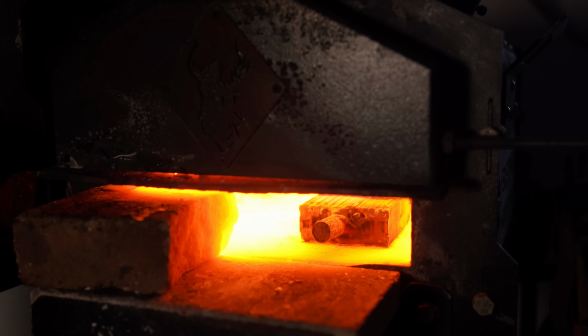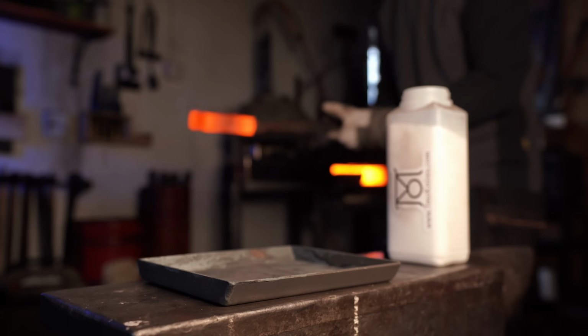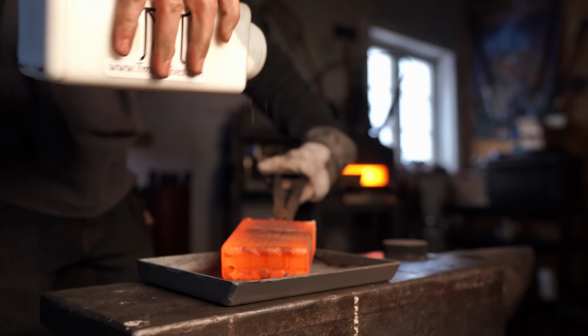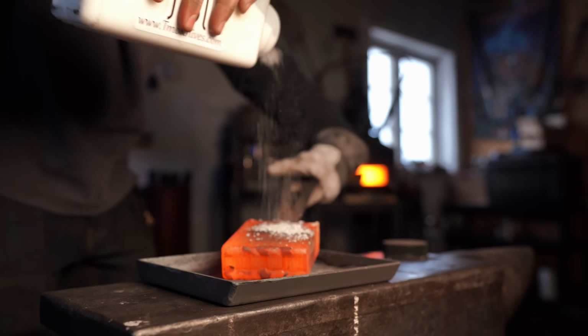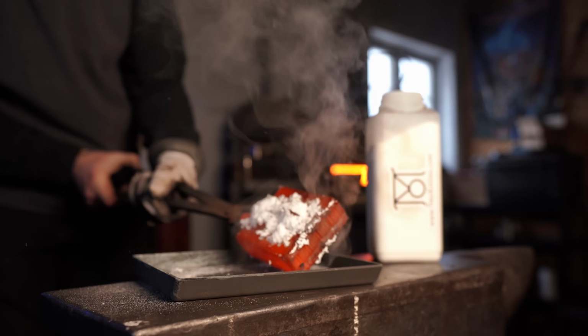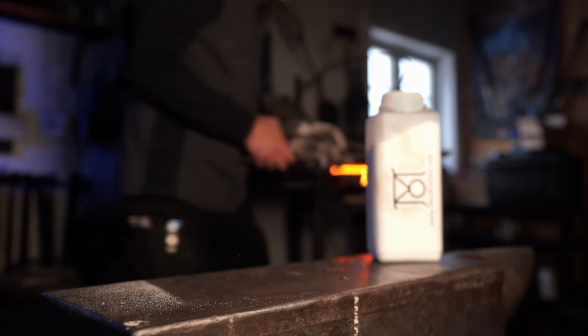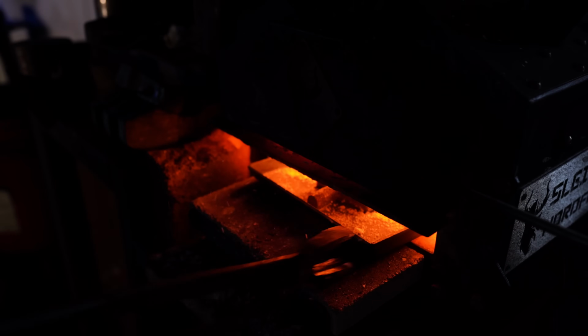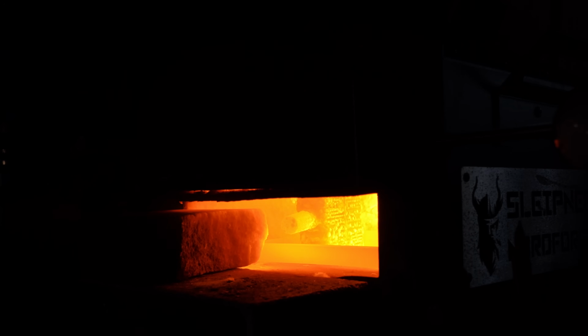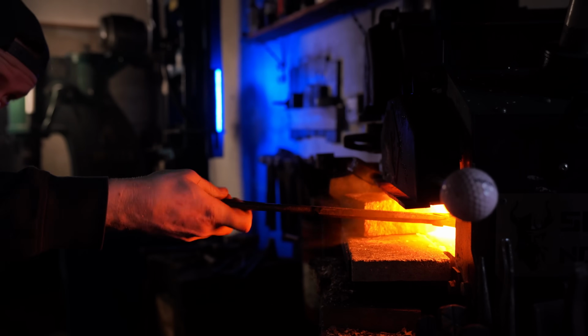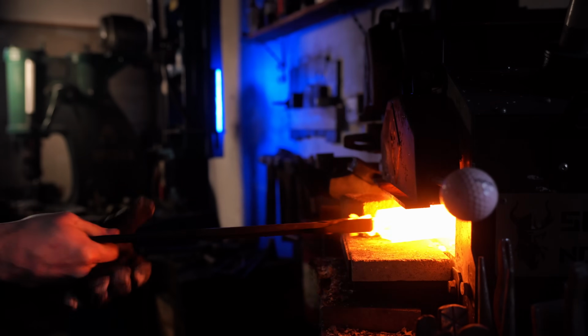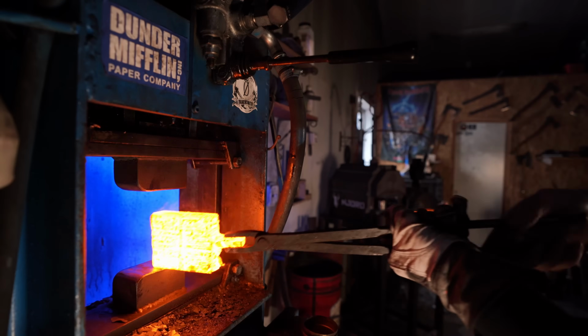Before bringing it up to welding temperature, I take it out and apply some flux to prevent oxidation and scale from forming. Now you have to do that while the steel is still relatively hot, otherwise the flux won't melt and form that protective shield. Once it's back in the fire, I bring it up to welding temperature and I forge weld it using my press.